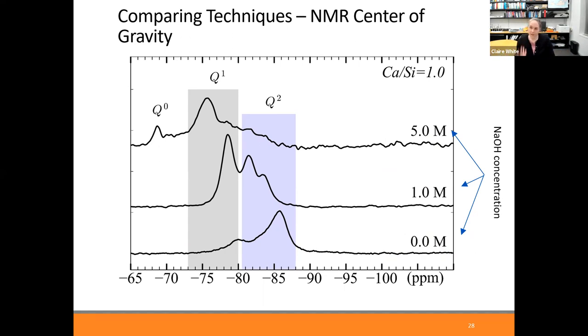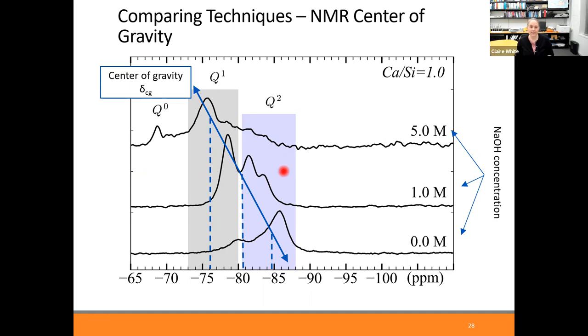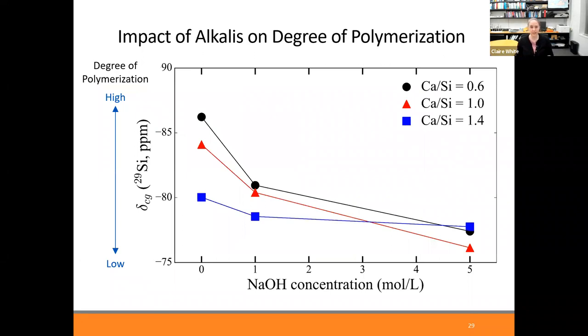Now, when the sodium content increases, what we find is that things are shifting towards the left on this screen. And so the gel is becoming more depolymerized due to the presence of sodium during synthesis of the gel. So we can quantify this change in silica connectivity by calculating the center of gravity for each of these spectra. And then I'm going to plot the center of gravity for a whole lot of samples on the next slide. This is what's shown here.